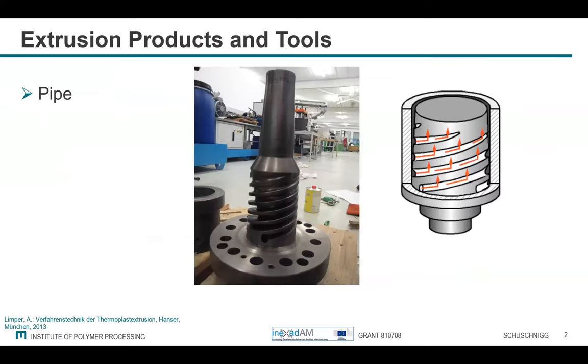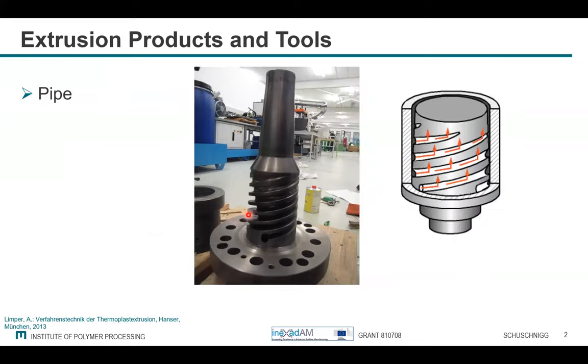The first thing I want to present are pipes. For example, here we have a spiral mandrel die, where we have these deep channels which are going around the core, and they are getting shallower and shallower. Then here you can see you are pressing the material out of these channels from the circular position to the axial. And up at the top, you get the melt out, and after calibrating and cooling it down, you get the pipe out of it.